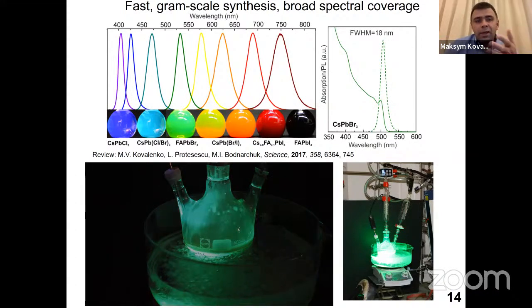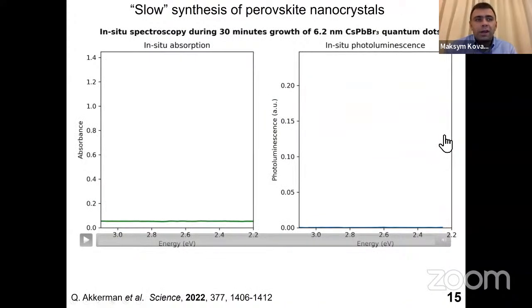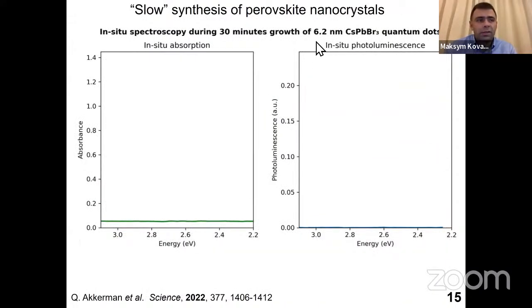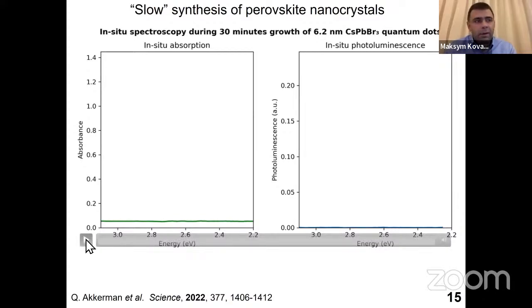At the same time, such a fast reaction is a problem if you want to have very fine control of the size, especially down to very small sizes, or if you want to grow some heterostructures and so forth. So for about 6 years from the first edition of the synthesis, we used only this type of chemistry, which was very fast because the ions co-precipitate very rapidly. But then 2 years ago, we began to explore a new synthesis pathway, and I show you the outcome of that new synthesis, which was just published last month.